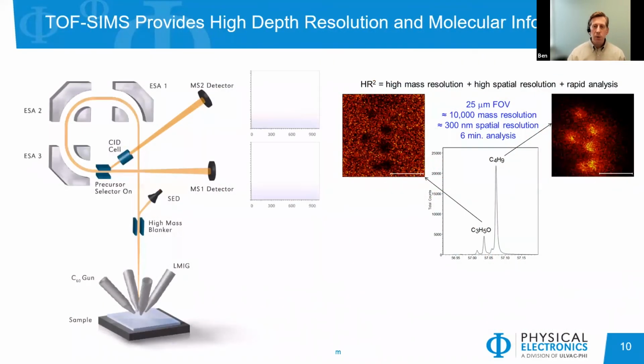And our last technique that we'll be talking about today is time of flight secondary ion mass spectrometry. In this case, we are using a primary ion beam, typically something like bismuth, to strike the sample and generate secondary ions. Those are directed toward a mass spectrometer where the time of flight separates the different species based on their mass to charge ratio. One of the nice features about this particular instrument, the NanoTOF-3, is that we have a tandem MS capability.